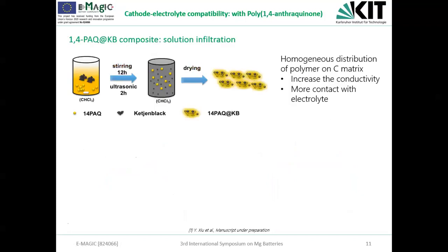Because we know that in principle the polymer material has relatively low conductivity, and with the normal preparation method we could only have very limited accessibility of this active material. That's why here we used a reprecipitation method, hoping to have homogeneous loading of the active material on a carbon matrix which has a high surface area, so that we could increase the conductivity of the cathode and also have more contact with the electrolyte. So we hope that by this approach we could increase the capacity as well.